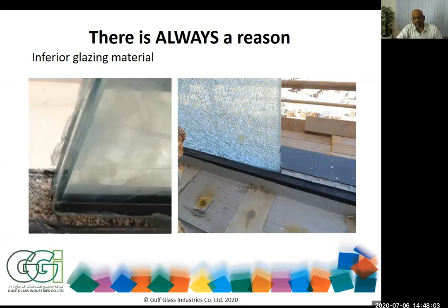The coefficient of expansion between glass, the metal and the grout needs to be considered. Glass has to have some expansion, because the building movement and the material movement will create such breakages. As you can see, most of the breakages were like this, and the grout was changed, and a wet glazing system was used. The right grout needs to be used. There are grouts which are specifically designed for glass balustrades, and that has to be taken care of.